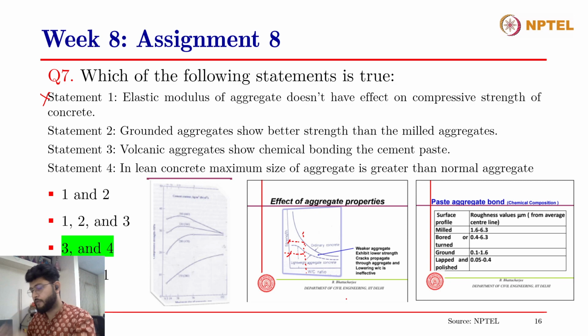So even if you try to lower the water to cement ratio, the strength doesn't get increased much, because previously, when the aggregates were stronger, the weakest link used to be the ITZ. Now that you have reduced the strength of the aggregates, the cracks can propagate through the aggregates themselves, and therefore the strength of the concrete will be lower in that case. All right. The second statement is ground aggregates show a better strength than milled aggregates, and here I've taken the